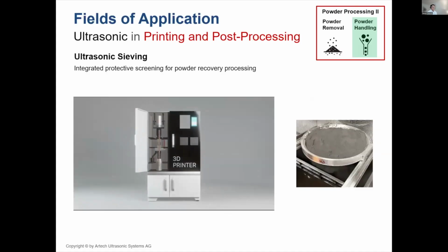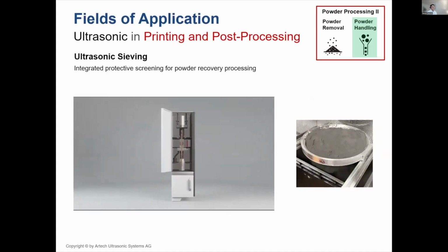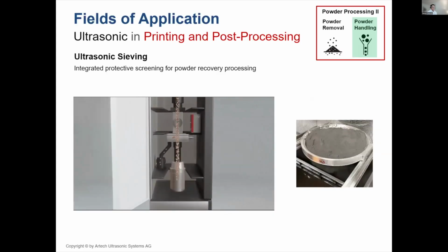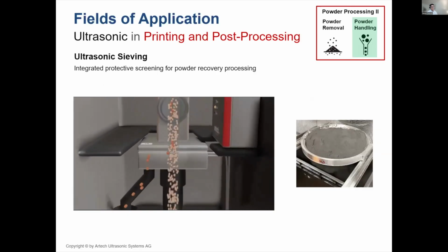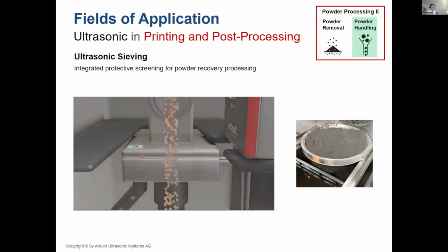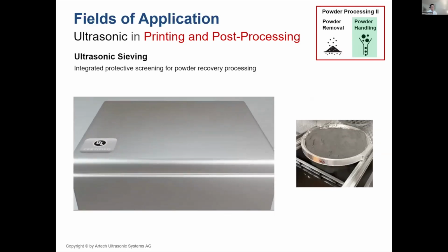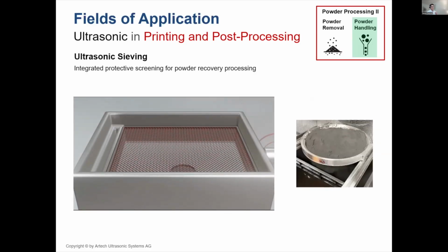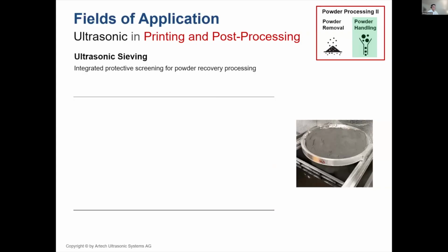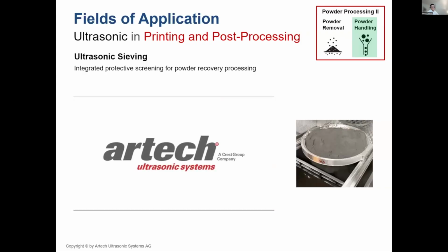As you can see on the top, the powder, in this case powder that is already used in the printing process, is put in a recovery process on the top, and then this powder falls onto the sieve. And the job of the sieve, as we outlined before, is to ensure that the right particles move into the next phase. So the undesired particles move out of the outlet. So at the end of the day, the end user wants to reuse this powder from the printing process back in his printing process, okay?